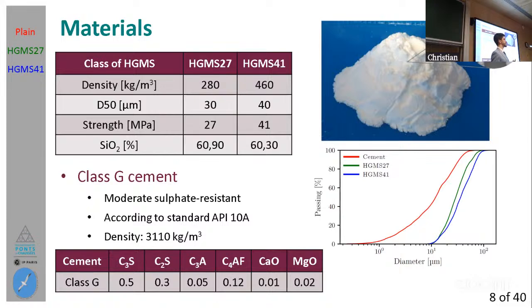Finally, I have used class G cement, which is a moderate sulfate resistant class of cement, manufactured according to the 10A standard of the American Petroleum Institute, and has a density much larger than that of the spheres, which is around 3,000 kilograms per cubic meter.